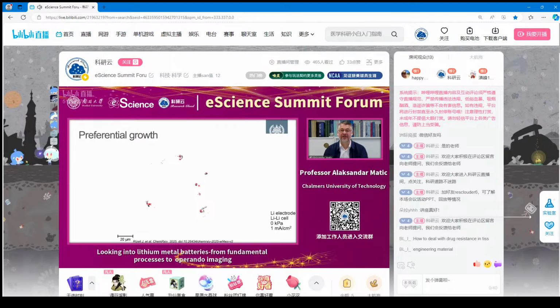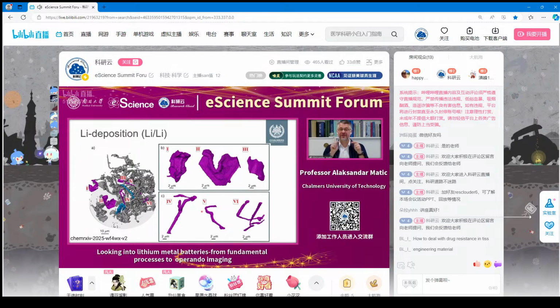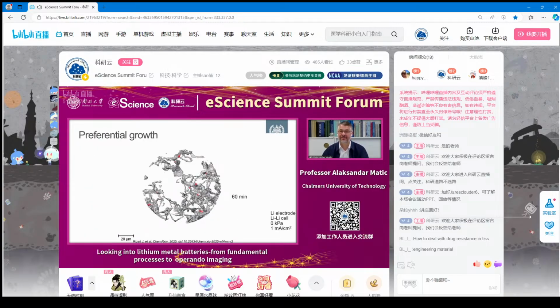So what we do now is that we take the electrode and we just flip it. So we look at the electrode from the backside, and the red points here mark where the lithium structures actually touch the bulk electrode. And when we now start to grow, after 12 minutes, you see that the number of points where the growth of lithium actually comes from the surface does not increase. So even after 60 minutes, we just have a few points which are in contact with the bulk electrode, which are the points of growth.